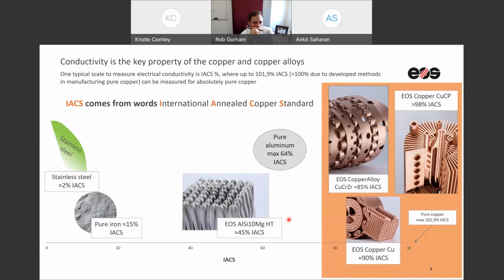Fast forward today, now we've got copper and different copper alloys. You're talking about pure copper, and even pure copper, you're talking about two grades of pure copper, which I'm going to talk about, which almost go up to almost 100% IACS, which means that you can imagine a full conductivity performance that you would expect from a pure copper.